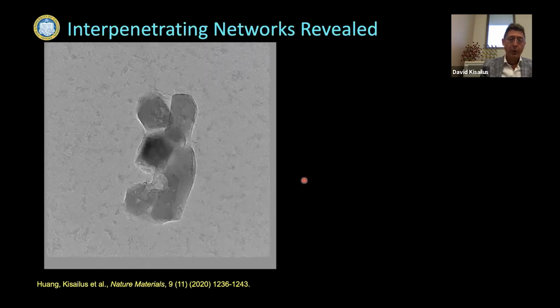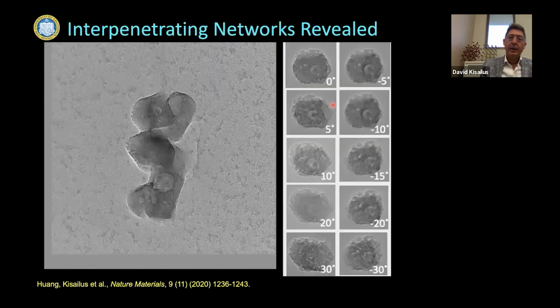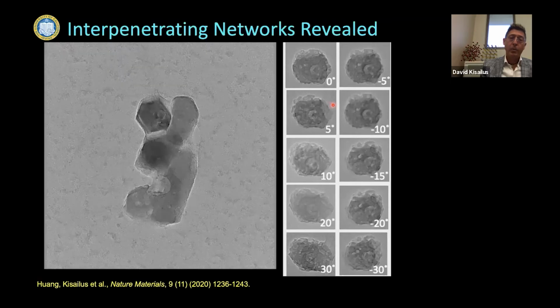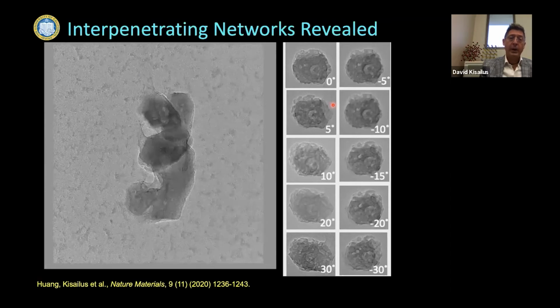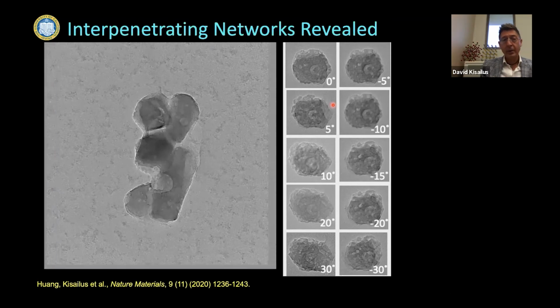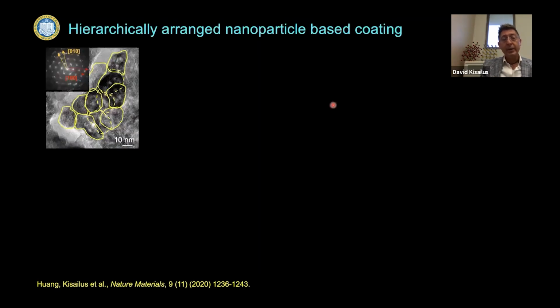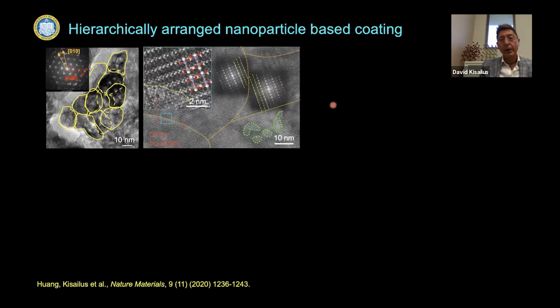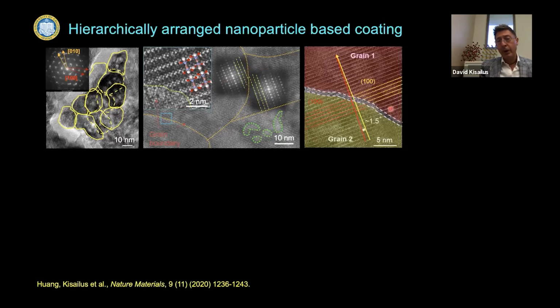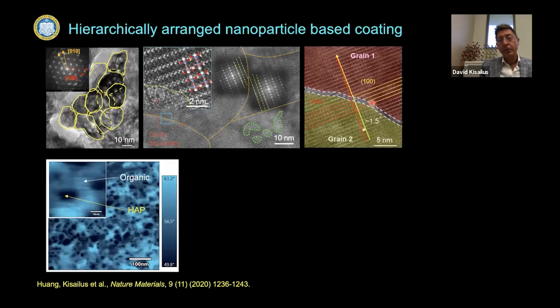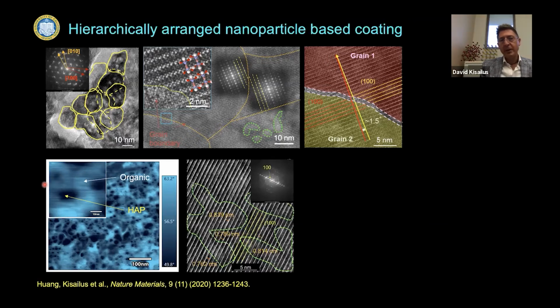So this is just showing a few of these particles. And you can actually see that there's an interpenetrating network of organic, what we would call a bicontinuous network of organic materials that are intertwined with the hydroxyapatite mineral. And within a secondary particle, a 60 nanometer particle, we actually find primary particles, single crystal domains that are stacked upon one another, but with low angle grain boundaries. And in addition, we've used AFM to show that the organic is indeed intercalated or interdispersed between the mineral phase, almost like a phase separated structure. So we see that, but we also see organic that's also occluded within the mineral.